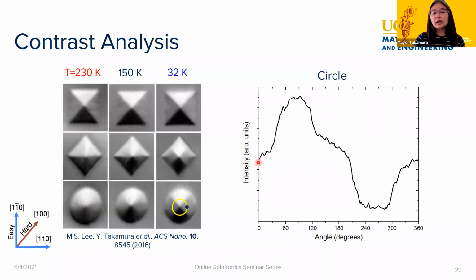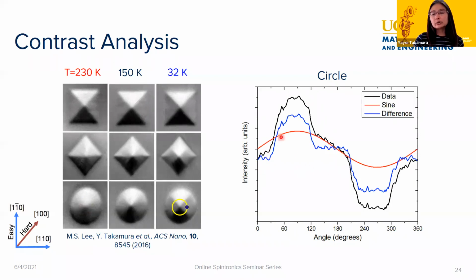And then we went to the circle at low temperature. Here, just by eye, you could say, oh, this is a Landau pattern, it should have just 4 colors. But what we noticed is that if you look carefully, these regions where it should be uniformly gray are actually not uniformly gray, they're sloped. And we could reasonably well fit that gray region to a sine or cosine function. So we could then deconvolve the actual raw data as a superposition of our step function, which is in blue, and the sine or cosine function. What that told us is that even though by eye it looks like we have a Landau pattern, what we actually have is still this vortex sitting on top of this Landau pattern.